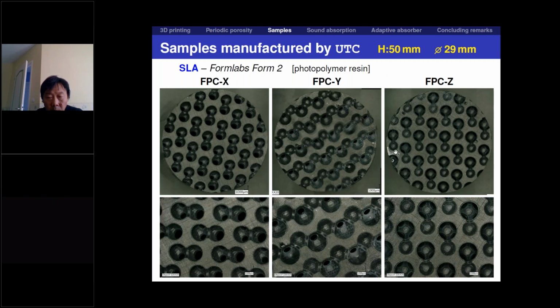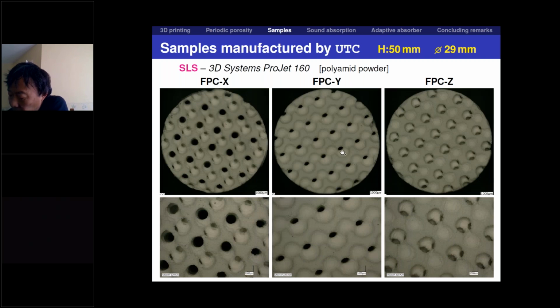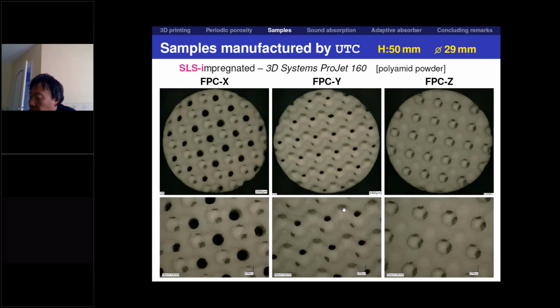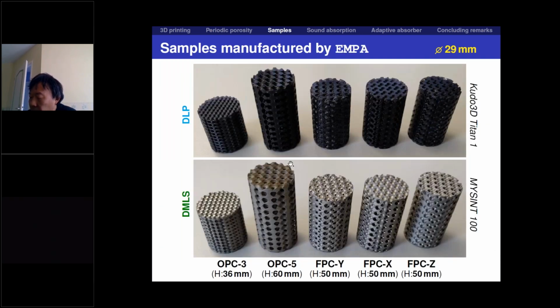These are very nice samples manufactured from resin using stereolithography. I treat them as reference samples with very nice, neat, smooth microgeometry. And UTC also printed samples from polymer powder, but with larger grains, not as fine as we used. So they realized that they actually have the effect of microporosities involved. Eventually, after measuring these samples, they also impregnated them and measured them again. And it will be very interesting to compare these two results.